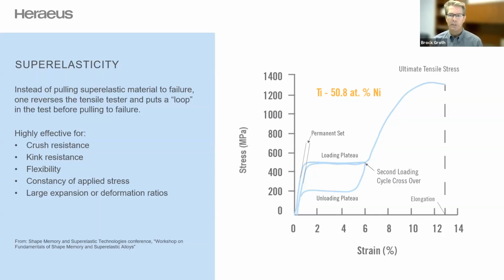And so what happens is you get this linear elastic section right off the beginning, and then at about 1%, at about 500 megapascals here, there's this loading plateau. That's where the material, again, you get a lot of movement with no increase in force. So you have this very constant force section. In this particular example, at 6%, the tensile tester is reversed.